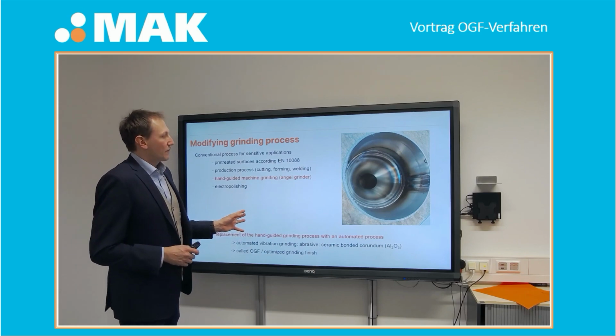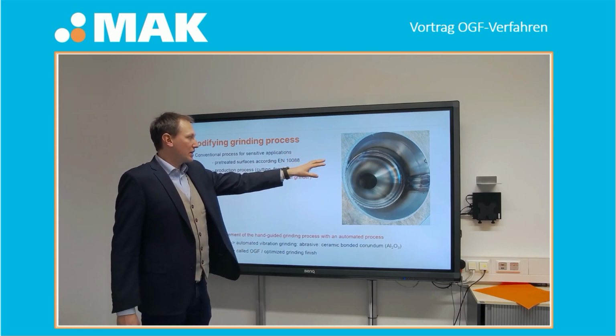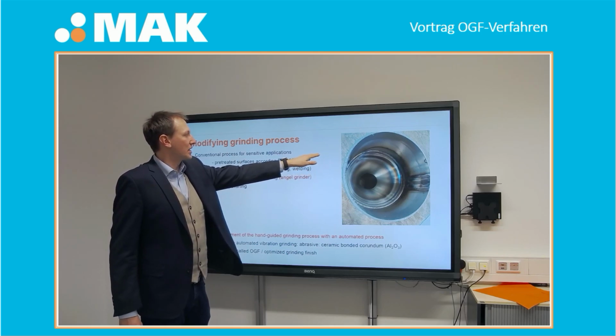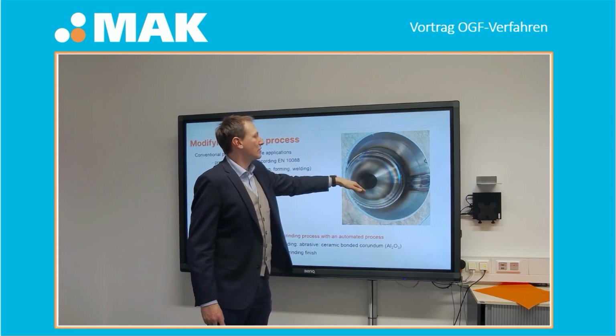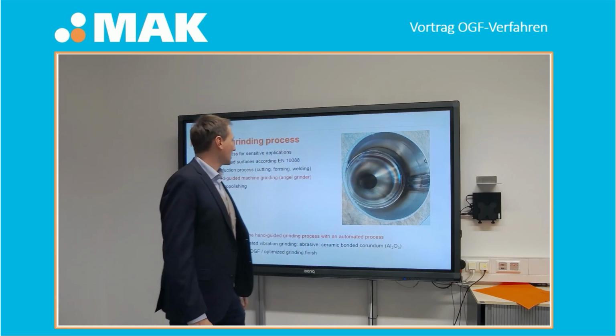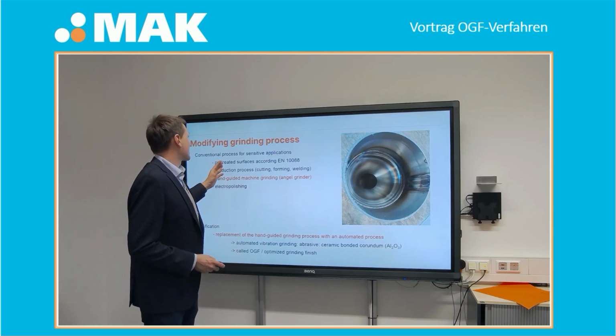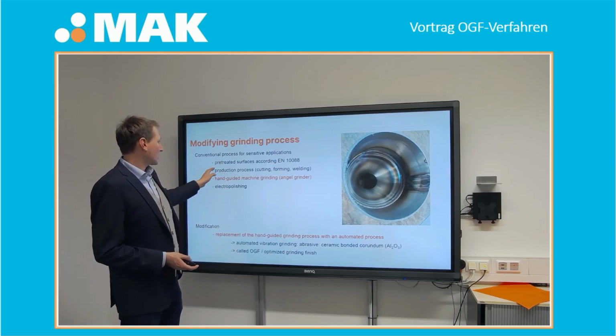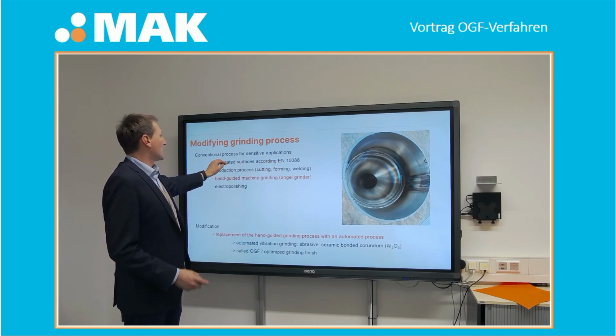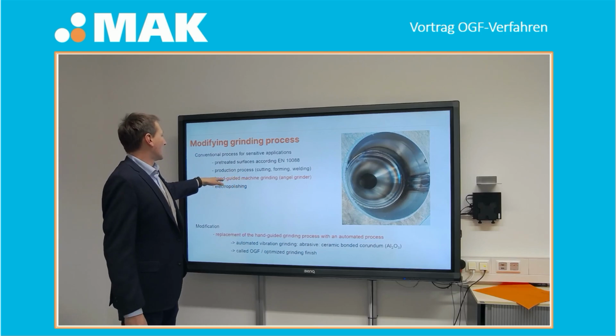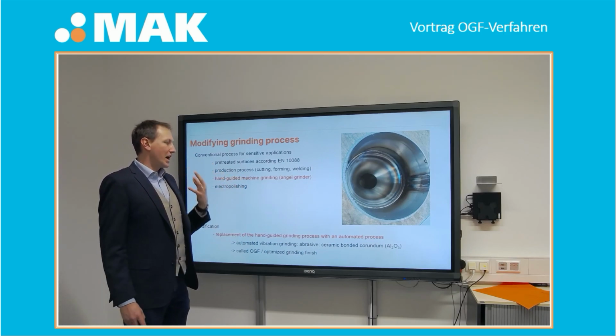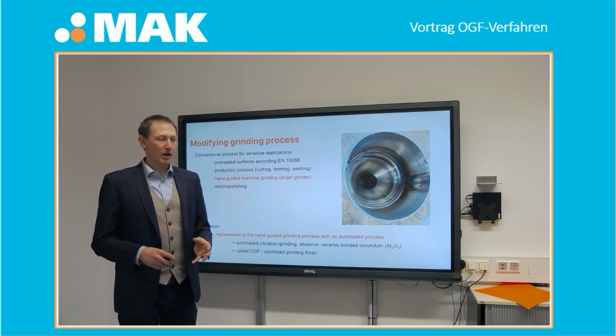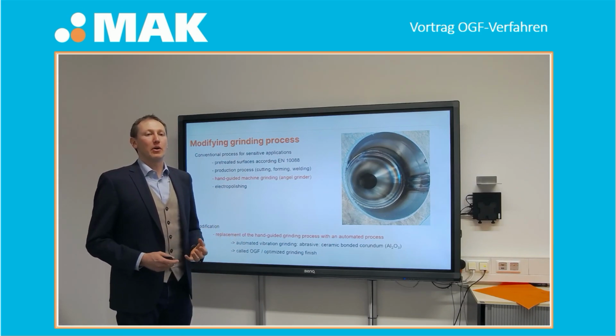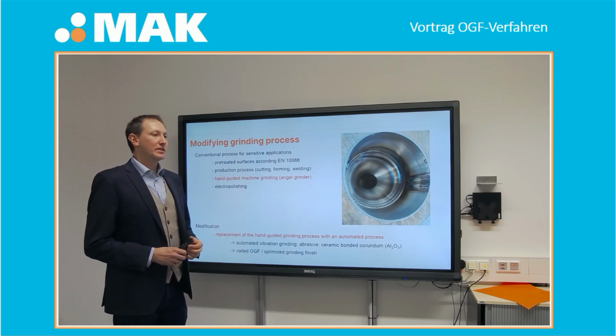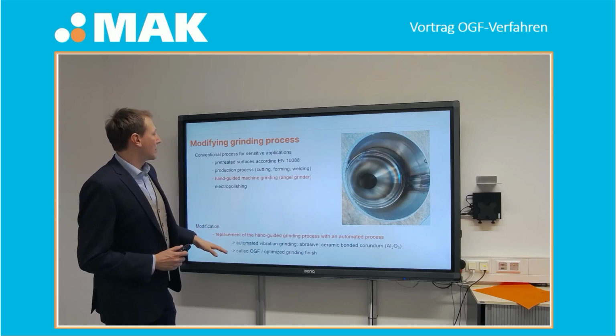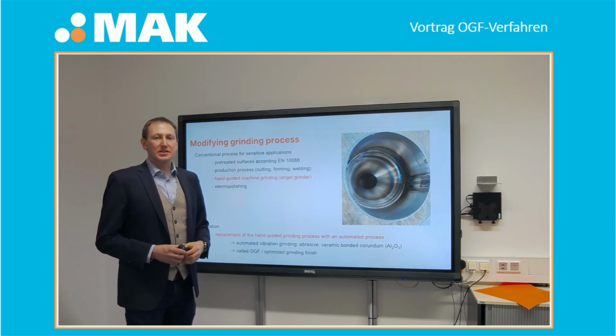If you're doing the manufacturing of a vessel like this, of course you have some rolling, you will have some grinding afterwards, and of course you have welding as well, so you have to remove the areas around the welds, and this is normally done by manual manufacturing processes. So you have pre-treated surfaces, you're doing the welding, the cutting, the grinding, then you mostly do a manual hand-guided grinding, for example with an angle grinder, and afterwards you do electropolishing on these vessels. And the goal of our project was to replace especially the hand-guided machining, because this is very risky.